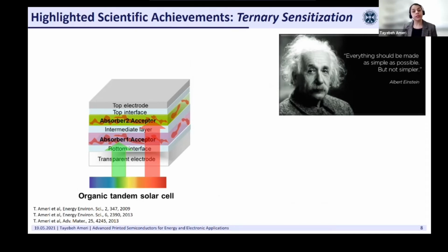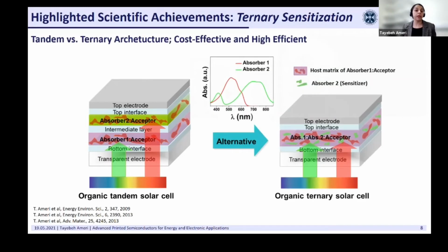And most importantly, if we think about the aim of our technology, which is printing in large area, then printing 10 to 15 layers on top of each other in a way that the top layer is not damaging the beneath layer is a huge challenge. So we were thinking, how can we get the benefit of this structure, which is a broader absorption profile, but stay with a simple single junction?